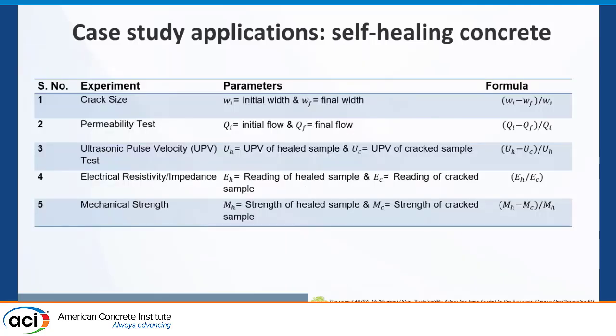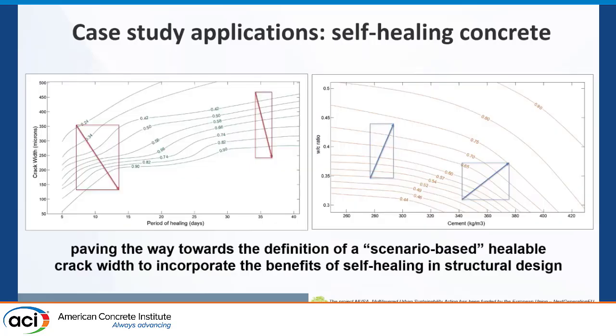Our output in this case were different parameters to quantify the effectiveness of the healing, so recovery in crack size closure, in permeability, in ultrasonic pulse velocity, and so on. And also in this case, we ended up with design cards. In this case, our goal was: which is the maximum crack size that in a given condition I can heal?